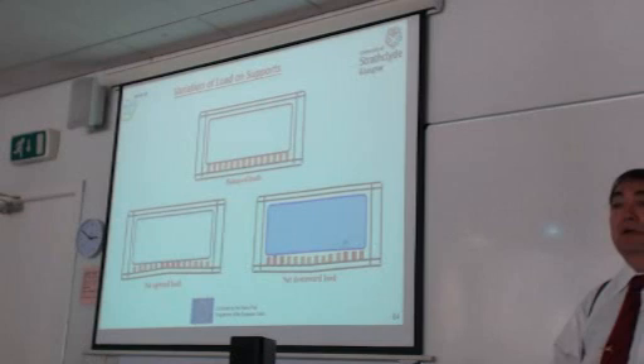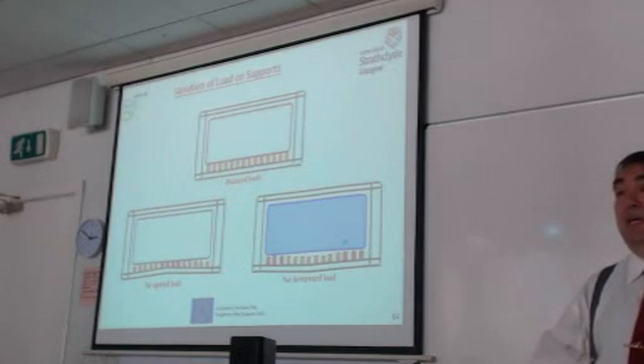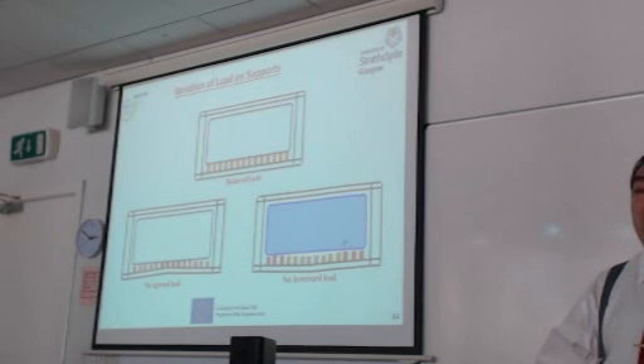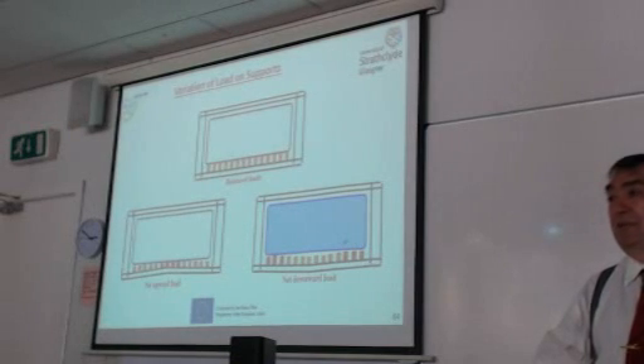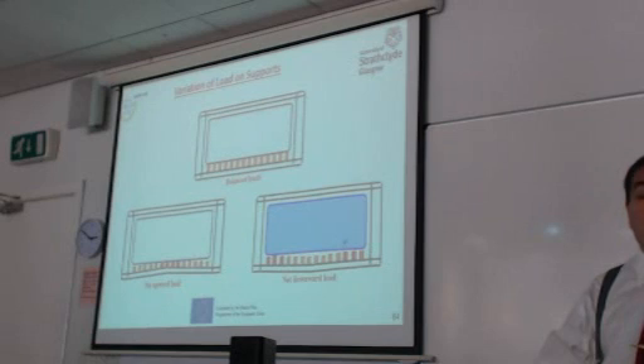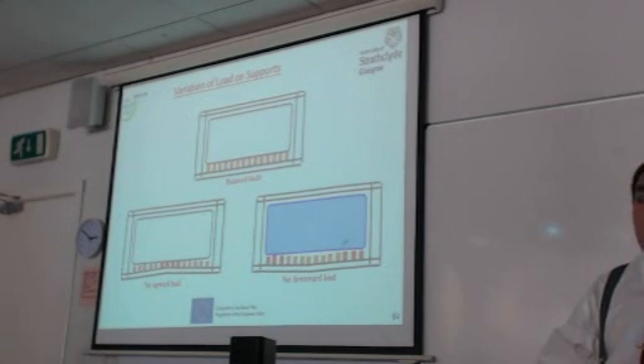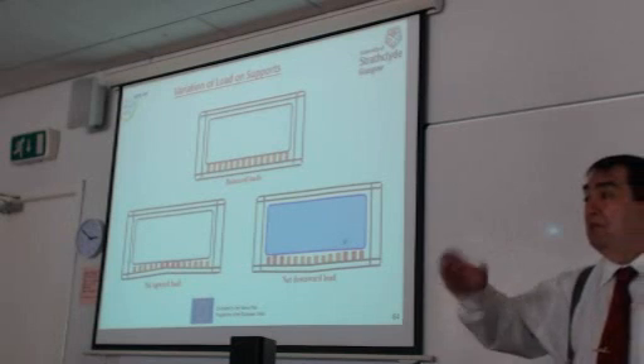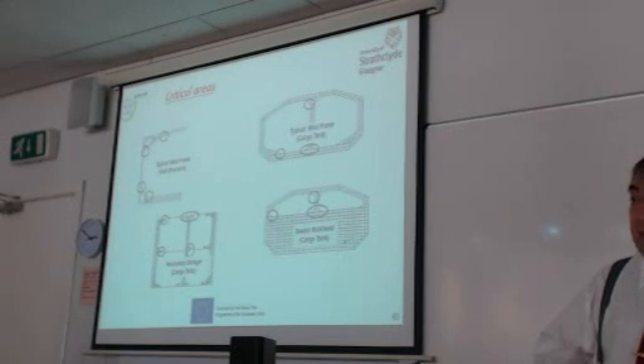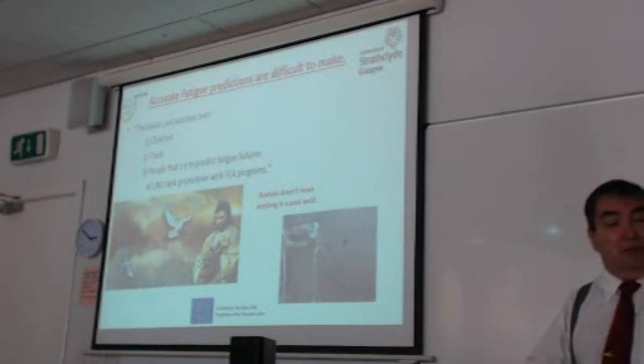So you realize that depending on the deflection of the ship, I will show you, we do not have uniform loading in all these supports. So to take the total number of supports, take the weight of the tank and the fuel, and split it among the supports is not a good idea, because the loads are not balanced. And you see here two different deflection patterns. The red ones are loaded, and the orange ones are not loaded. So this means you have to do an iterative cycle. I'm afraid I have to show you, these are the critical areas that are typically loaded.